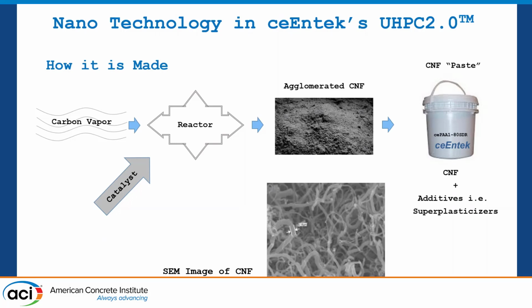So the way that these nanofibers are made is we're using a carbon vapor material. We're adding a catalyst in a reactor, and we're making our carbon nanofibers, which are dispersible in water, which is a real key. A lot of times if you try to do this, it's all going to clump together, and you're not going to be able to get that dispersion, so it isn't going to go everywhere. It just becomes a little clump. We don't want that. We want it to go everywhere. We add that in with superplasticizers and some additives, and that is supplied as the additive that you're going to put with that sand cement premix, and add water. Sometimes you can add accelerators and fibers, and now you have a UHPC.